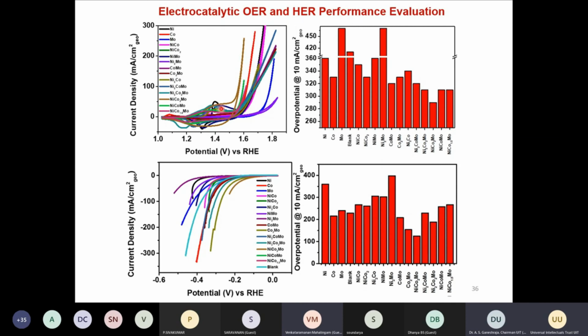There are too many curves, please don't worry about them, but I have shown this bar diagram where we measured the activity, that means calculated the overpotential at 10 milliamp per centimeter square for all these materials. What we found is that nickel-cobalt-molybdenum shows very good activity compared to the others, for both hydrogen evolution as well as oxygen evolution. This is the oxygen evolution and this is the hydrogen evolution reaction.